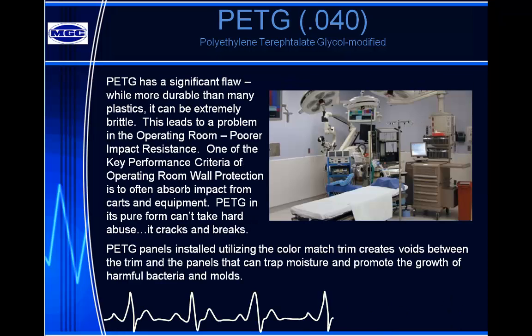PETG has a significant flaw, however. While more durable than many plastics, it can be extremely brittle. This leads to a problem in the operating room: poor impact resistance. One of the key performance criteria of operating room wall protection is to absorb impact from carts and equipment. PETG in its pure form cannot take hard abuse. It cracks and breaks. PETG panels installed utilizing the color match trim create voids between the trim and the panels that can trap moisture and promote the growth of harmful bacteria and molds.